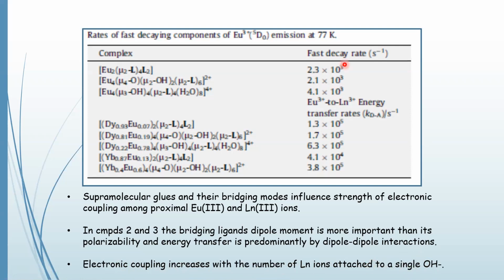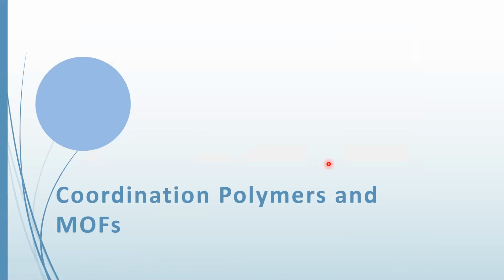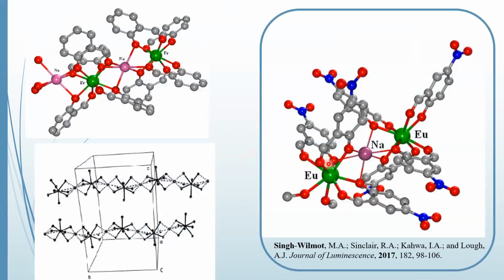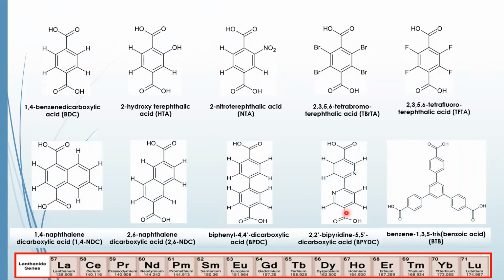So having done that, we were able to go on to the coordination polymers and MOFs. And I will just summarize some of our findings here. We started with some simple coordination polymers. These were linear coordination polymers, the crystal structures we defined, and we saw they were one-dimensional chains. And we did some luminescence work to show, in this one, we have lanthanide ions, europium, bridged via sodium ions. We were able to show that the sodium would interchange, and there were some dynamics between the sodium ions and the lanthanide ions interchanging positions. But then the framework materials we went into, which is what I want to focus on now.